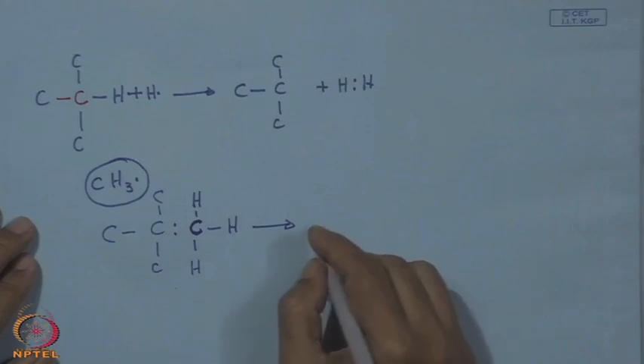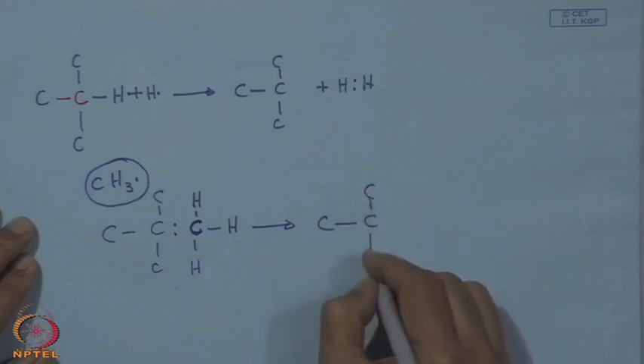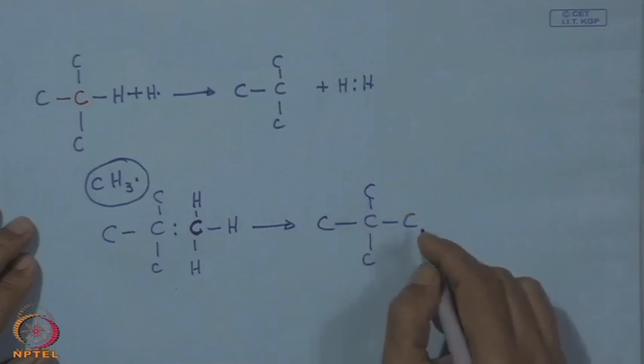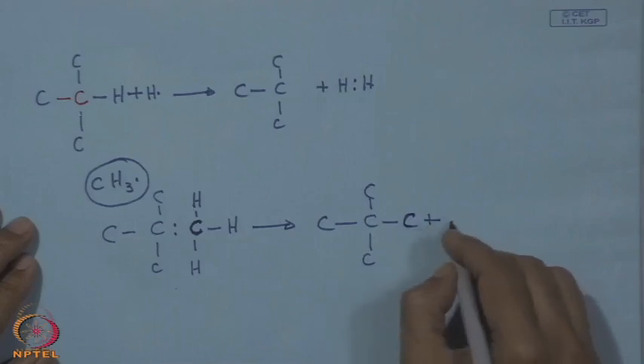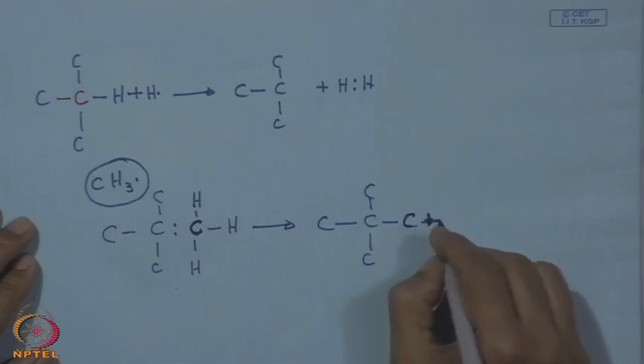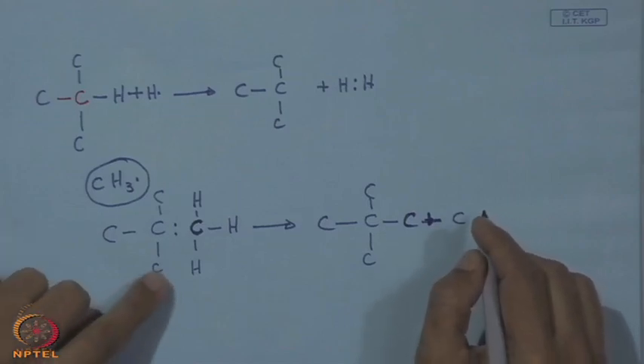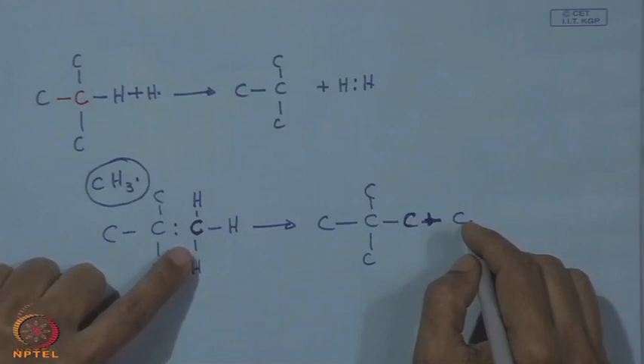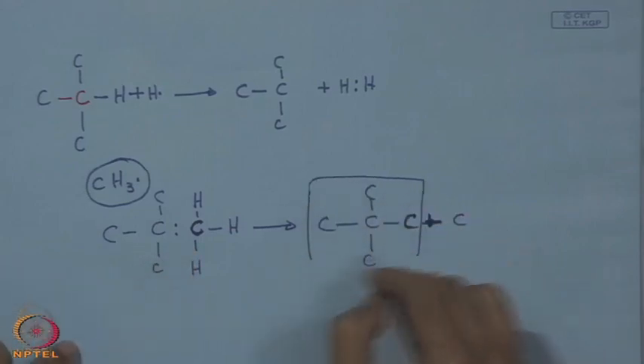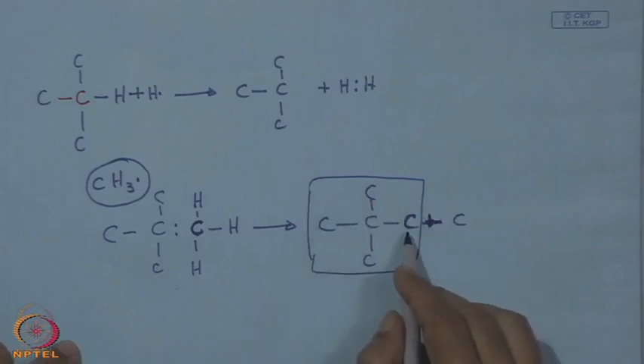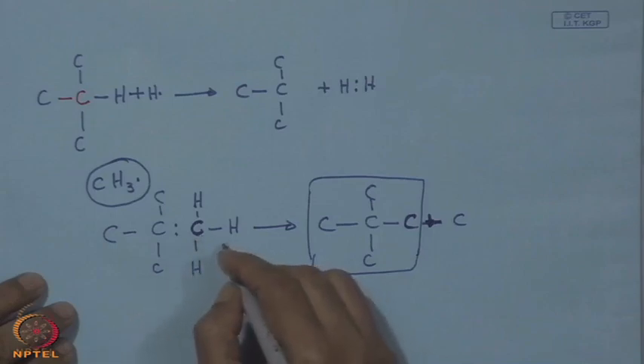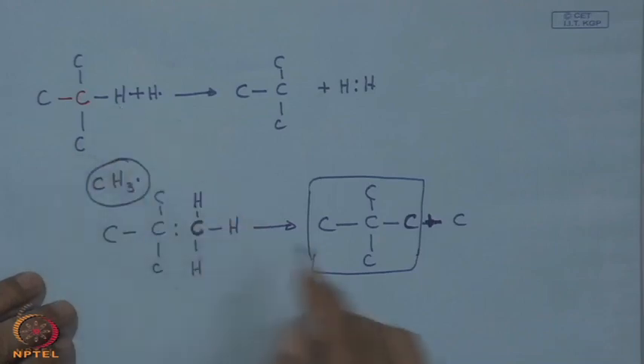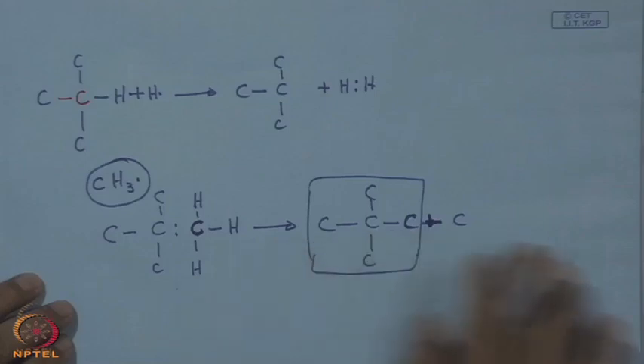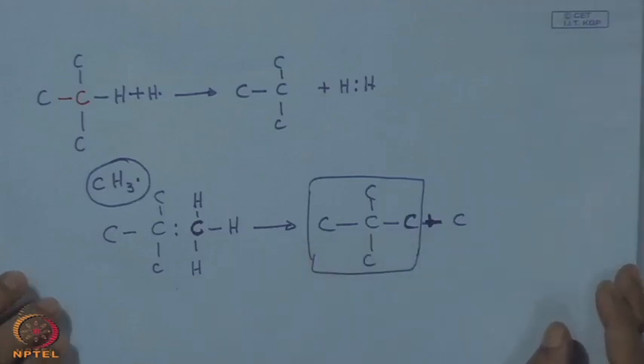So, what we finally see here is that we have a complete lattice of diamond, that means this site is no more vacant, and we have here this C, and this will keep on moving in every direction, and we get this complete filling of this atomic site. So, on every location, wherever you have that removal of hydrogen, that will be filled in by this methyl radical. So, this way the diamond coating will keep on growing. So, this is actually what we know as CVD reaction.